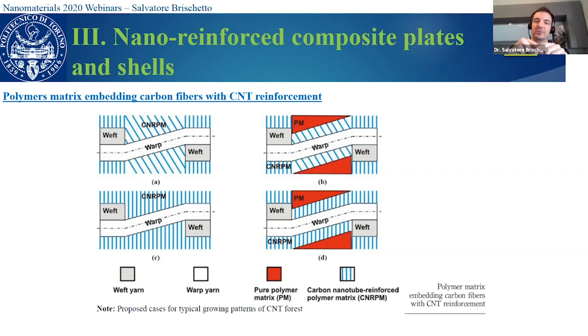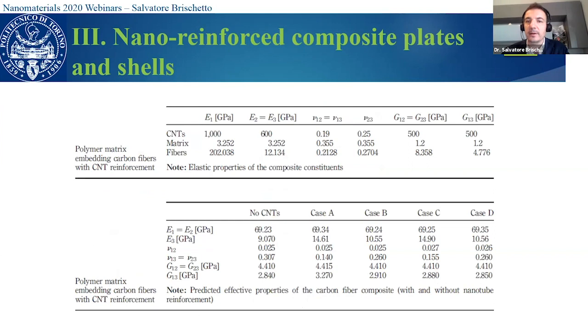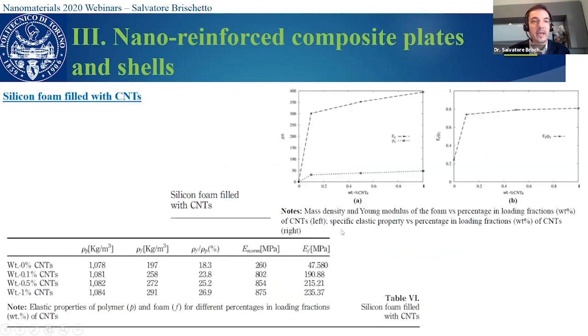Okay, these are nanotubes added to the single fiber, which allow to improve the adherence between the matrix and the fiber. So, for example, we can see these are the 4 cases explained in the figure, and this is the example of the multi-layered composite structure without carbon nanotubes. When we add the carbon nanotubes in each single fiber, we improve in particular the transverse normal Young modulus. Okay. Another possibility is the silicon foam.